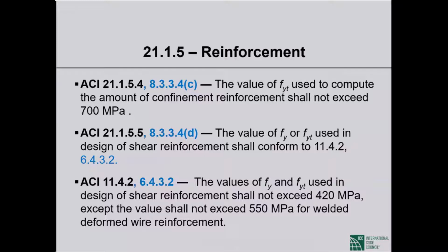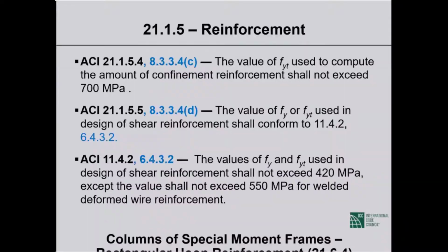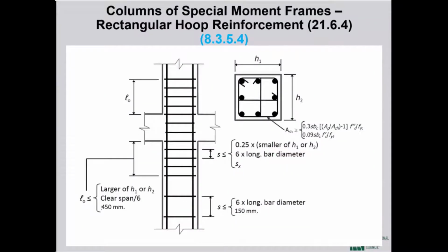The second restriction applies because if we use high strength reinforcement, if we allow somebody to use f sub y much more than 60 ksi in shear computations, there will be very likely major shear cracks, which we do not want in our concrete members. Okay? The shear reinforcement will yield, the shear cracks will get wide, and that can cause significant problems. So for confinement purposes, high strength transverse reinforcement is fine, but for shear, the high yield strength of the transverse reinforcement cannot be used in computation. In computation, you have to use something no more than 60 ksi.